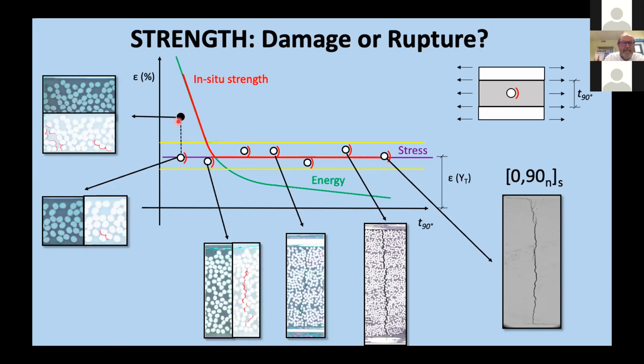isolated debonding. But probably we will never get these values, because previously the value corresponding theoretically to a total damage, total transverse rupture of the 90 degrees lamina, because probably previously you will have the total failure of the laminate due to the failure of the 0 degrees lamina.